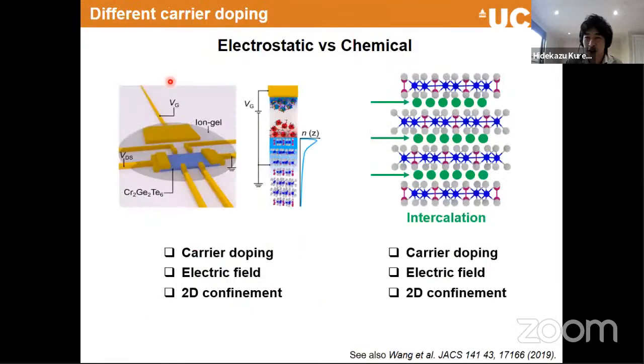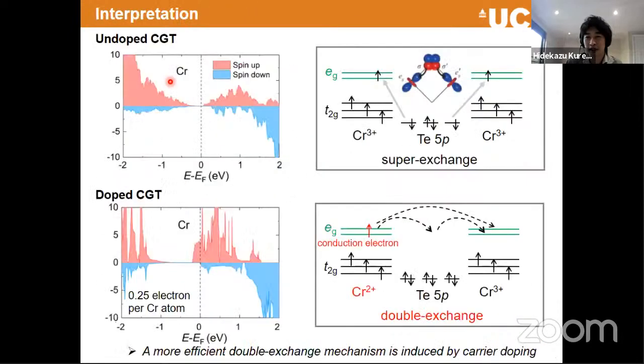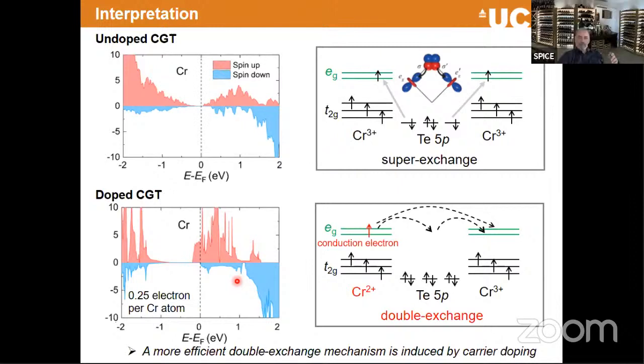So I can just quickly go back and spend a minute to explain it. This one, the electric gated one. What we did is, first of all, we measure the carrier density by Hall transport, the Hall effect. By using this value and an assumption that this is purely 2D, single layer, we can calculate how many electrons per chromium atom we dope.